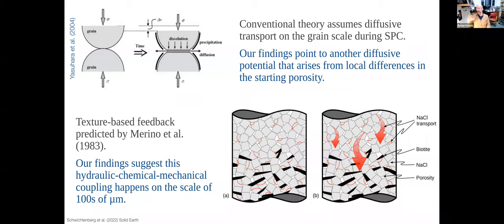Now, the sample is uniaxially loaded. So there's an externally imposed stress, bulk stress on the sample, which is distributed over the grain contacts. If the porosity is locally higher, then you have higher stresses on the smaller contact areas you have, and slightly lesser stresses on the biotite in the biotite bearing domain, right? And that gives rise to a concentration gradient, which we think is being exploited here. That hasn't been observed before.